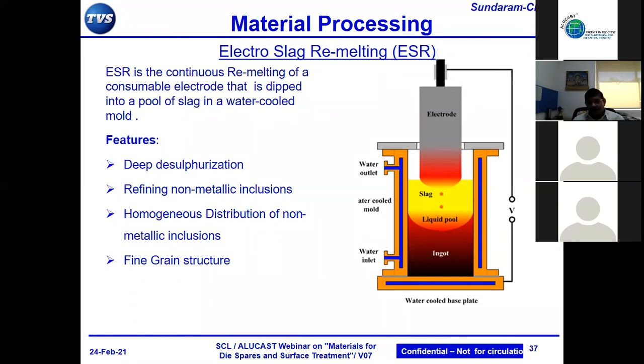In fact, when I've gone to a few mills, I could see this kind of segregation based on the number of reuses of this slag. And that is what actually happens when you give different grades of material. And this manifests again in the performance of the insert.